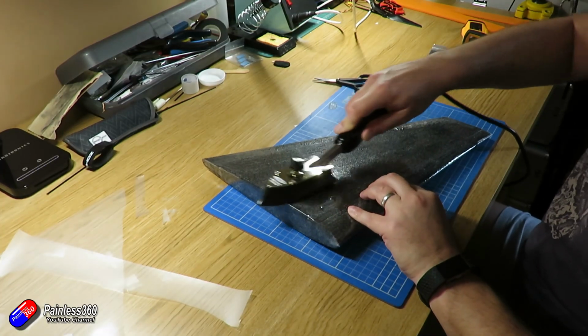Now, you'll be able to spot whether or not your iron is too hot or not. First of all is if you are running it over a regular injection molded wing, you will notice that the surface, if the iron is too hot, will start to look like the skin of a lizard. All of the little individual round pieces of foam will start to overinflate, and you'll end up with this lizard skin effect. That's usually a sign that your iron's too hot. It's probably going to be in the 170 degrees or hotter. Stop what you're doing, check the temperature of the iron. If it's too hot, then turn it down, let it cool down, and go back to it. I know some people quite like that effect. Personally, that just looks to me like the iron's too hot.